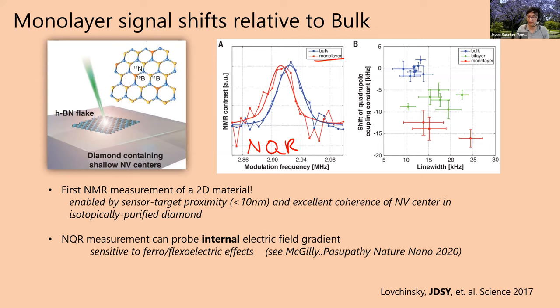And so what we're observing here is that the monolayer hBN has some internal electric field gradient, which is different than the bulk. Which maybe is not so surprising. What we now know about these materials, especially boron nitride, is that they're really sensitive to strain inside the material. So if you strain them out of plane, they develop electric fields, and so it's not so surprising that in the monolayer form, there's going to be some different strain structure compared to bulk.